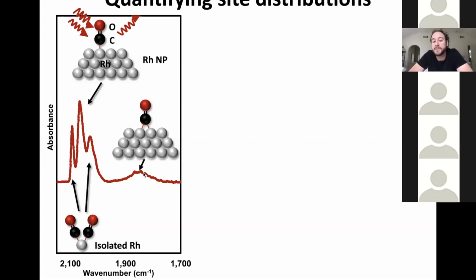These bands have been rigorously assigned by many people to a few different coordinating environments for CO. If CO is linearly bonding to a rhodium atom on a rhodium cluster, you get a stretch around 2060. If CO is bonding in a bridge fashion to a rhodium cluster, you get this bridge-bonded CO, which has a stretch down around 1850 or so.